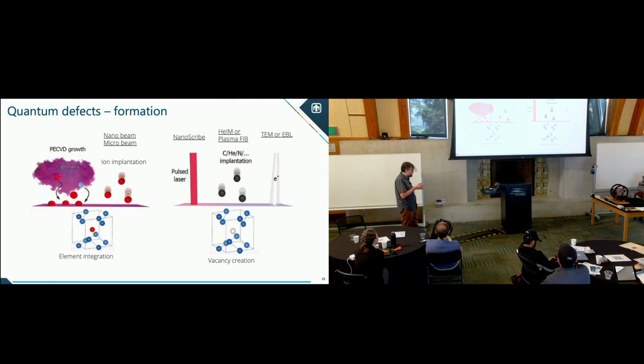So you get a very high energy focused laser beam, and you can damage locally. You can do implantation either locally with something like a helium ion microscope or plasma FIB, or do broad beam implantation of helium, for example. So you can hit it with helium. Helium's not going to stay in the diamond, but it'll leave damage.